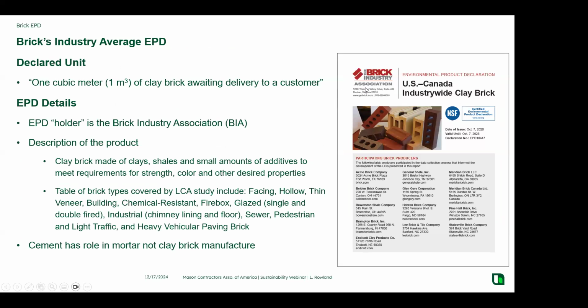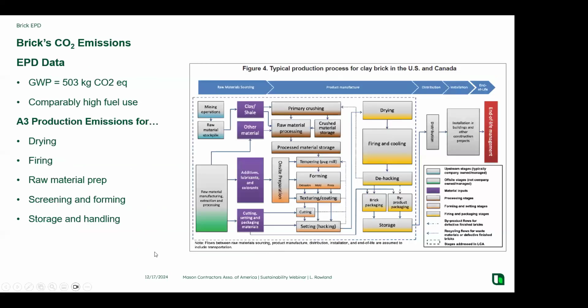The BIA has produced their own environmental product declaration. The industry average EPD is for all these different types of bricks. So they've gone through and they explain that clay brick is made with these materials. These are the different types of bricks that were studied and included in their study. So it's a very broad range. So if you utilize brick, you can pretty much count on this EPD covering that type of brick. And of course, cement has a high role in the production of mortar, but not in clay bricks. You don't have the cement as a factor here. So the A1 associated with brick is very low because essentially your A1 is your material extraction and the mining of that clay and just the processing of the clay and getting it ready to fire and make the brick.